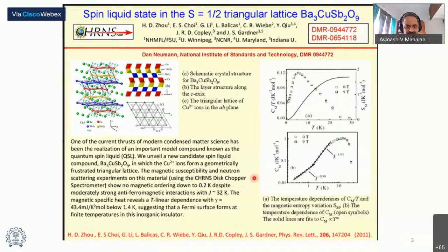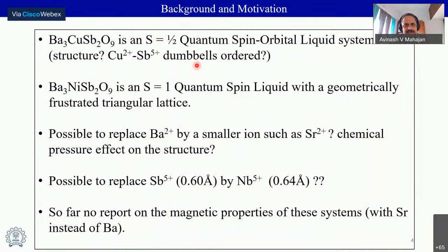Well, it turned out later that this is not as simple as it looks. There are different structures that are present. And even then, there are still novel features. So you have these Cu and Sb dumbbells, and you could have them ordered or disordered. So it could go into a honeycomb or a triangular geometry. But nevertheless, in various kinds of geometry, they still showed interesting ground state properties and also low energy excitations. Even replacing the spin half with a spin 1 nickel also gave very interesting properties.